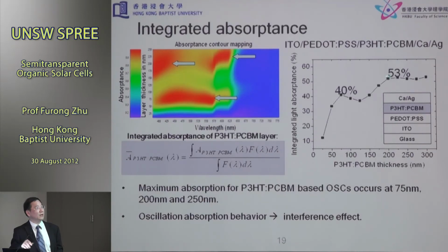So you can find that the absorbance of the layer in the blend layer oscillates. It's very interesting that at certain layer thicknesses, for example here close to 75 nanometer, the thick blend layer has a relative maximum in terms of light absorbance. And with further increased layer thickness, for example to 120 nanometer, if you're using a 120 nanometer thick blend layer, it does not absorb more light than a device with a thinner layer. This is because of the interference effect.